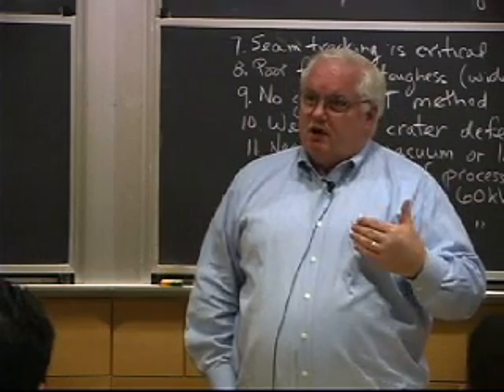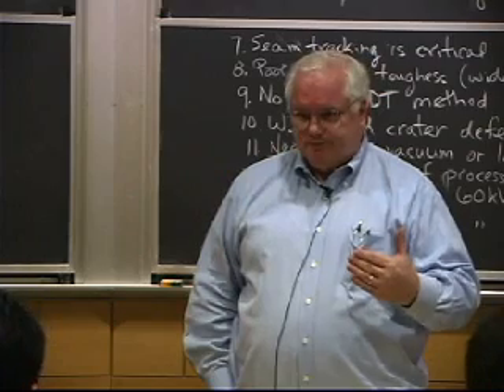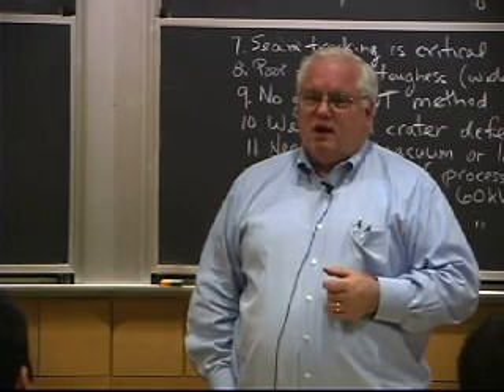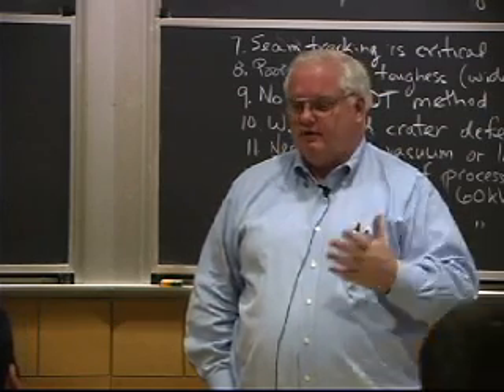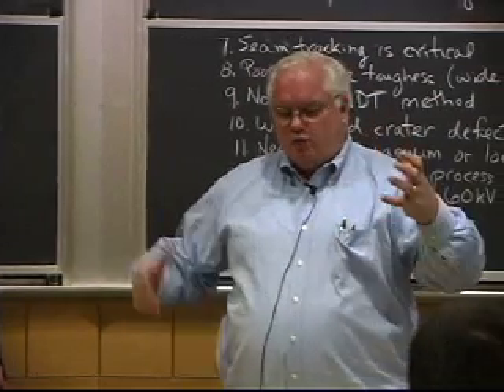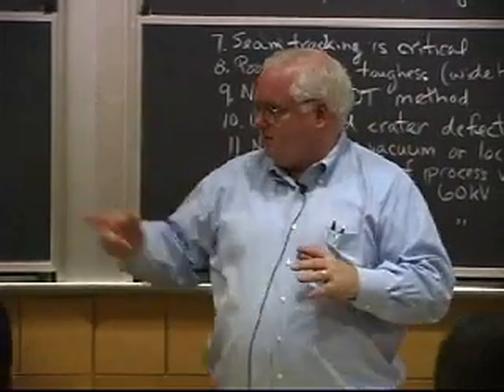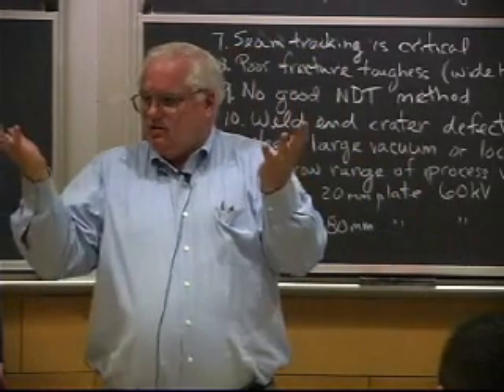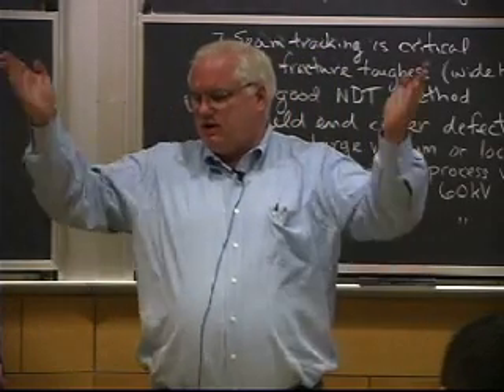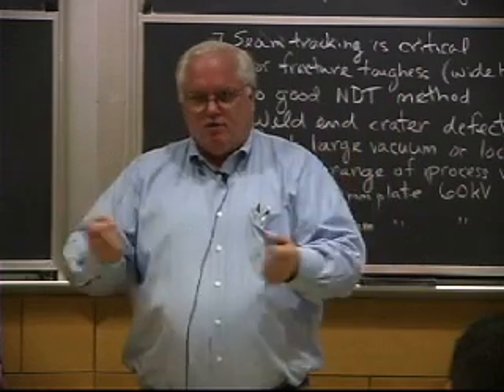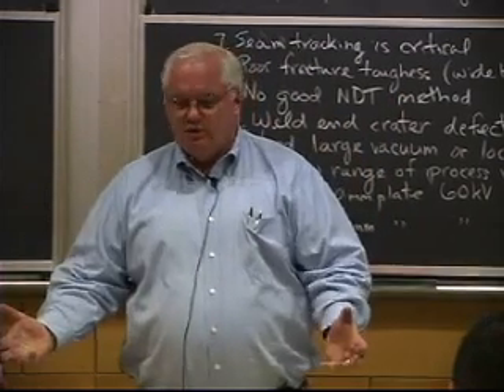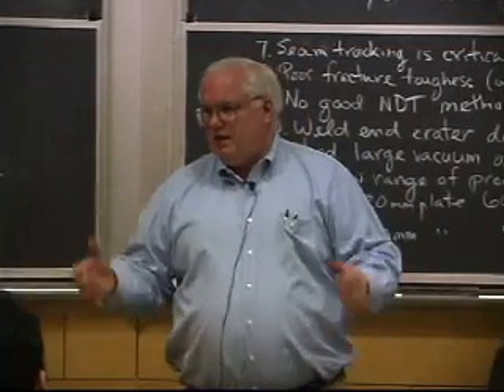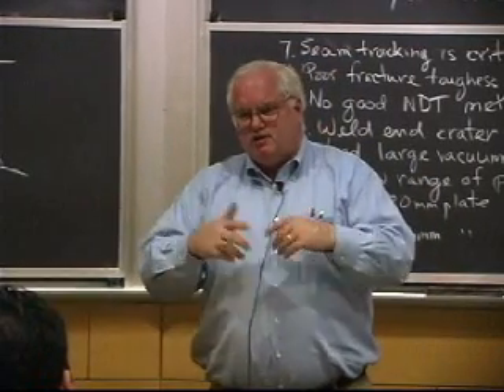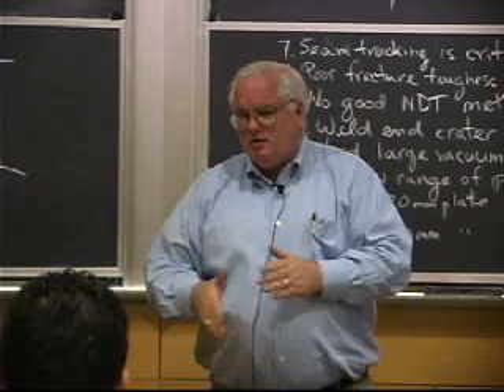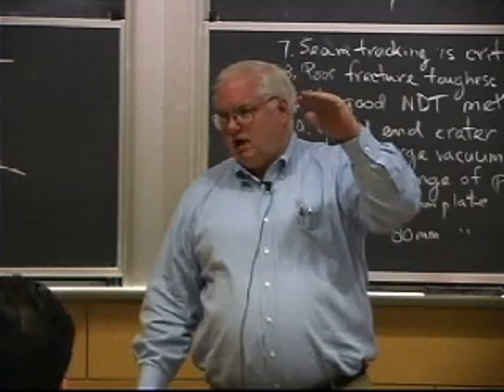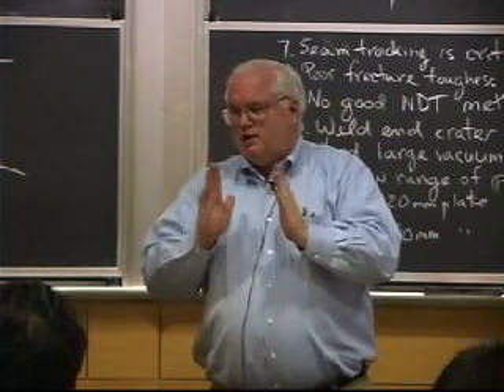And about 15 years ago, they had a crack in one of the I-beams at the one in Worcester. It was a fatigue crack. The thing had been used for 30-some years. And they basically had welded some pads. Now, these pads were not small, about the size of that overhead projector. And they were basically just pads to support it. The beam on the ends had some sloping sides, and they just welded this thing on so it would be horizontal so they could hold it when they were putting it in place. And they never cut these things off, and they left it there, and you had a notch there, and a fatigue crack started. It wasn't necessarily a bad weld, it's just a notch. This I-beam was 10 feet tall, and the web was 10 inches thick.